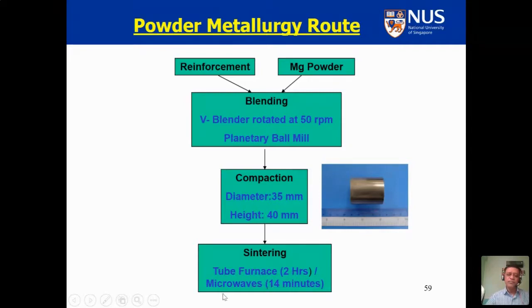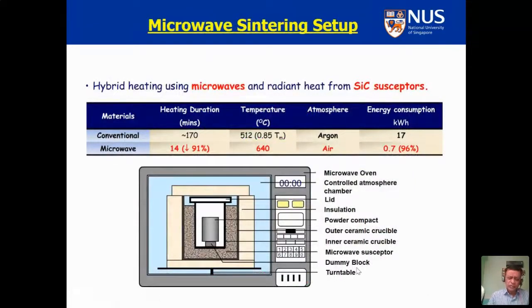And the difference we made was that we started using the microwaves. So how does the microwave work? We created a setup from a microwave which you use in your home. So it is not something very special or out of the world or very expensive. It costs you like $1,000 in the market. So we created a setup in which you take two crucibles, inside crucible, outside crucible, and you fill with silicon carbide, which works as a microwave susceptor in here, and then you enclose that into an insulation cover shown by the yellow areas here. You pre-calibrate the microwave setup, and for every minute you can record a temperature.